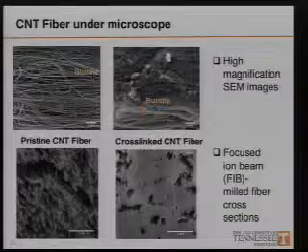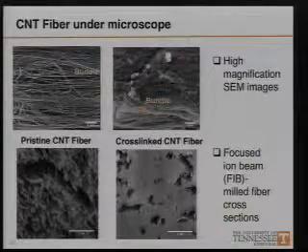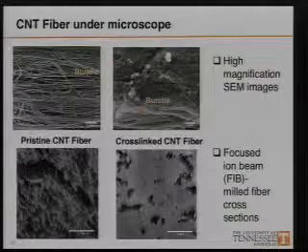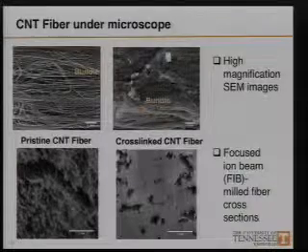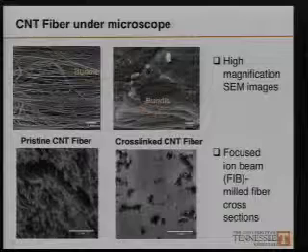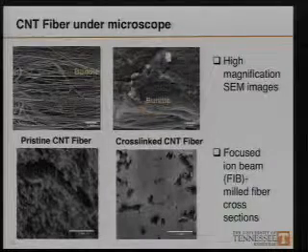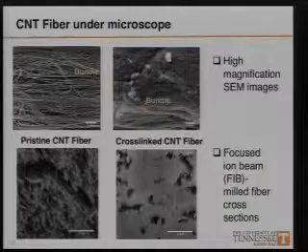In order to check the internal structure, a cross-section has been acquired using focused ion beam milling. Again, it confirms that the void spaces have been reduced and a continuous phase has been introduced into the system.